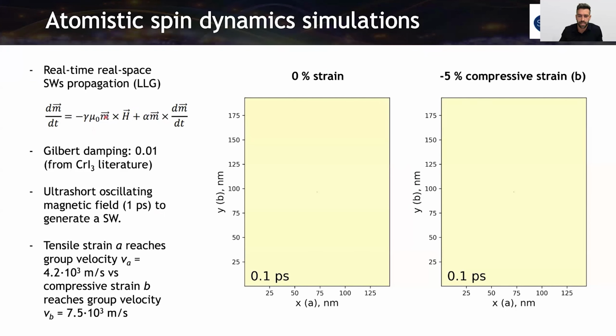In this case, we are applying Gilbert damping from the literature, taken from chromium iodide 3. This is just empirical for chromium iodide 3. And we apply an ultra short oscillating magnetic field during 1 picosecond to generate a spin wave. Here we can observe the effect. This is with the material without any kind of strain.